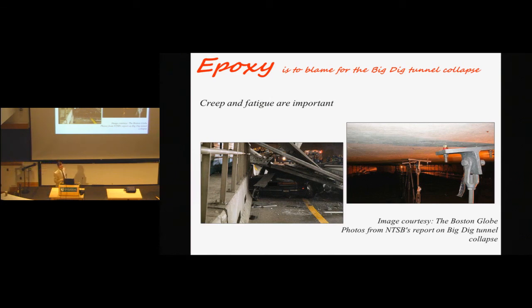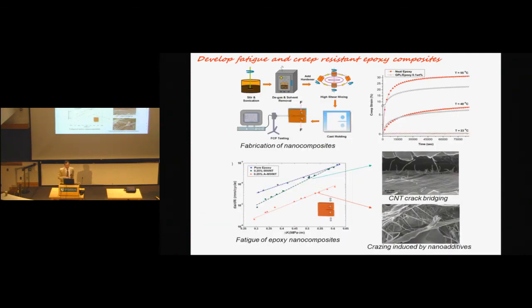So in our research, we try to improve these two properties by adding inclusions, by adding nanoscale additives to epoxy. Here are two results which I would like to share with you. We produce these composites by mixing epoxy with carbon nanotubes, with graphene, with functionalized graphene and carbon nanotubes, all right? And then we test their properties. We test the fatigue properties and creep properties.